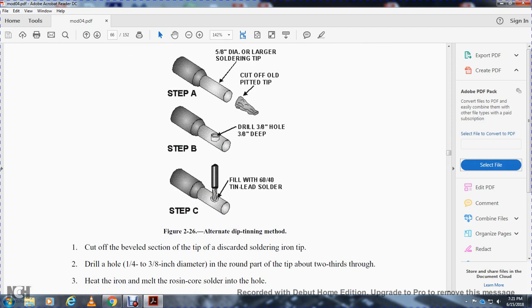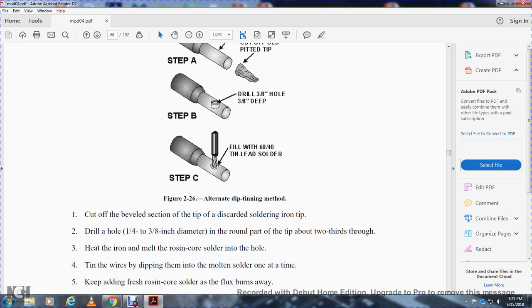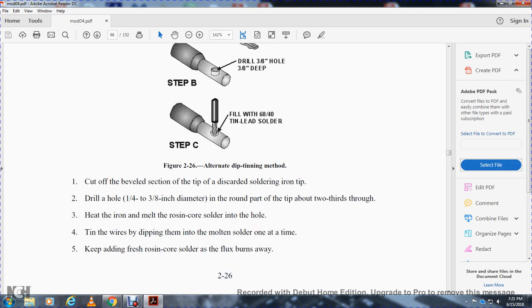Step C: cut off the beveled section of the tip, discarding it from the soldering iron tip. Drill the hole 1/4 inch, 3/8 of an inch in diameter, part way through the tip. Heat the iron and melt the rosin core solder into the hole. Tin the wires by dipping them into the molten solder one at a time. Keep adding fresh rosin solder until the flux burns away.